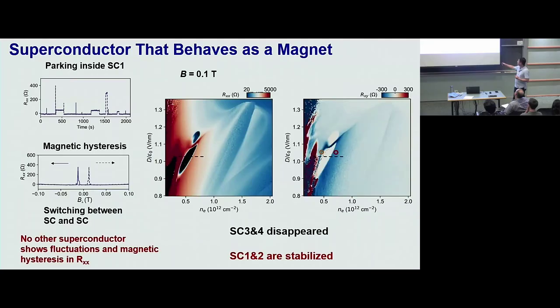Okay, first of all, SC3 and 4 are gone. Okay, this 100 millitesla is too big for them. However, SC1, SC2, they got stabilized. There's no more fluctuations. Not only in the superconducting region, but in this big region right next to it, there's no more fluctuations. So the system really got stabilized by outer plane magnetic field.